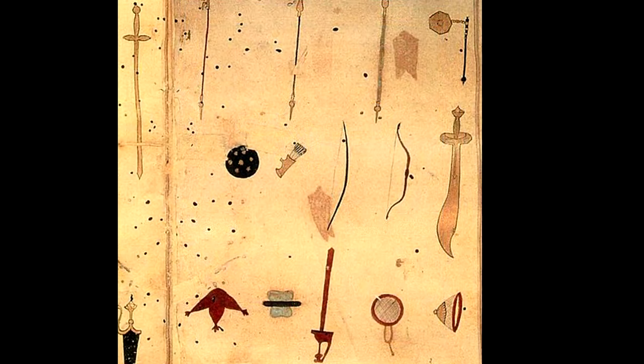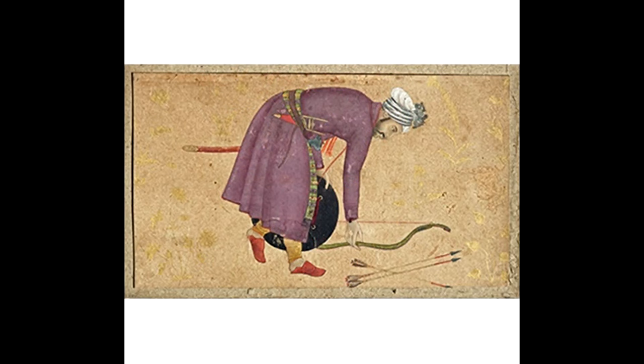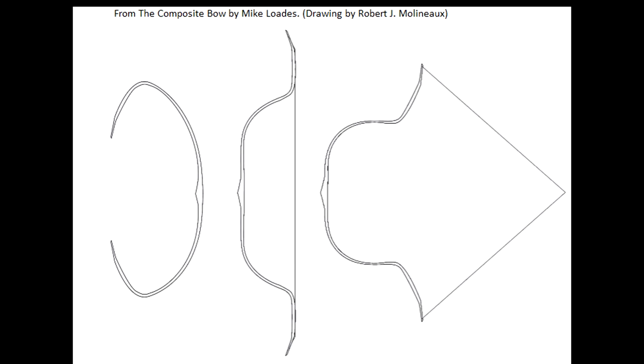By the way, the Mughals didn't just use this specific bow design — they had various other ones such as self bows. But the bow I have today is based on the command design, but made of fiberglass. Historical Mughal crab bows had a very extreme recurve design, and making such bows requires high craftsmanship and skills in composite bow making. Unlike typical Ottoman Turkish bows, the limbs of the crab bow are usually wider to reduce twists, allowing the bow to be left strung for longer periods. The siyahs are very stiff and non-flexible, forcing the entire bend into a tiny portion of the limbs alone.